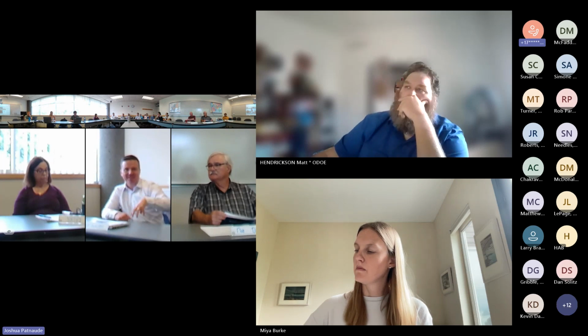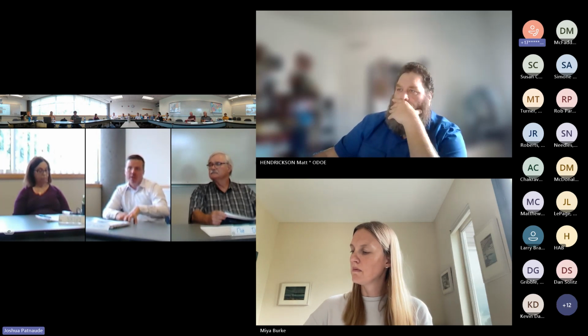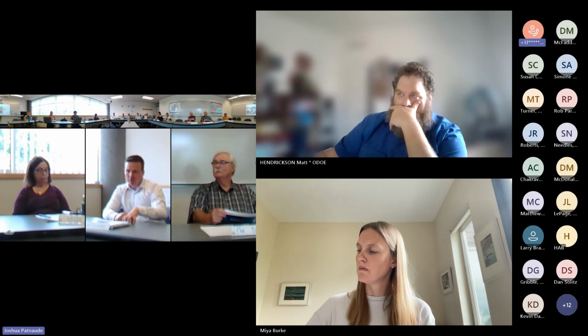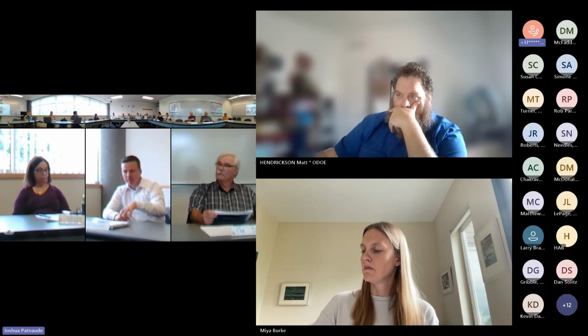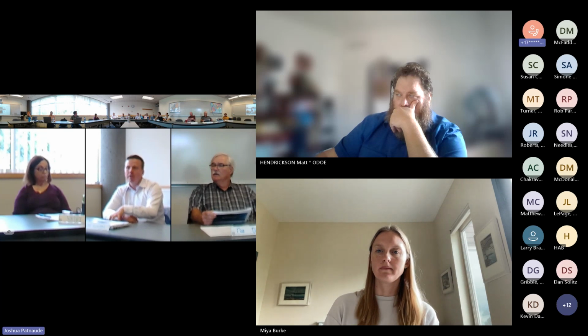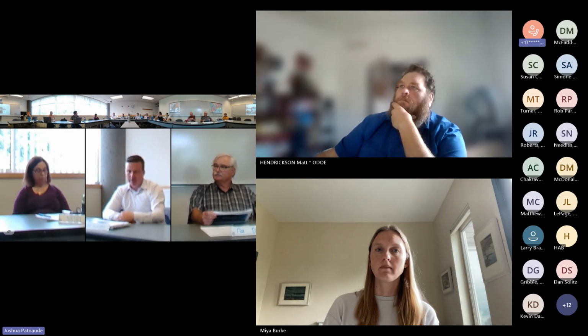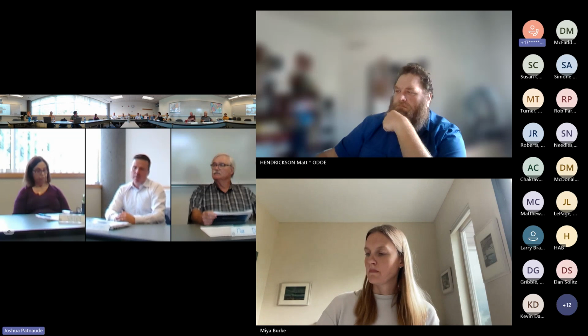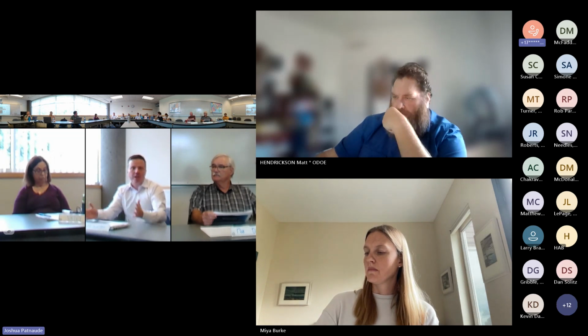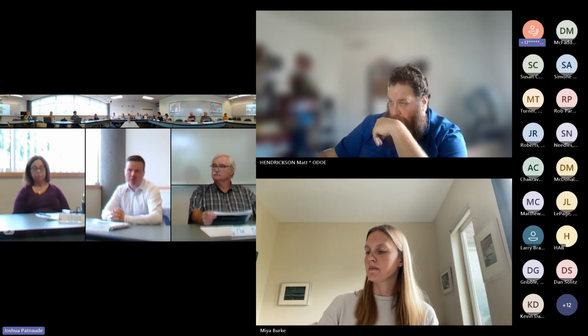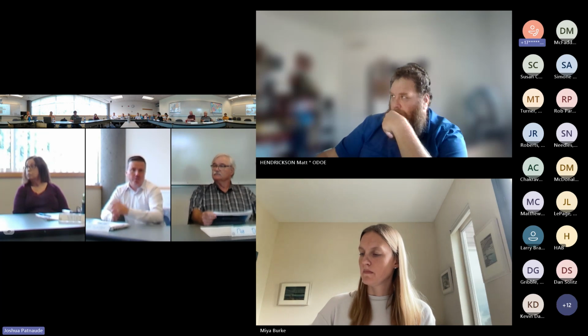So everyone's getting all the information of here's what we're seeing. We did some developmental work, some screening work with a simulated SY-101 waste composition, to see how your treatment method worked for it. They did what they were intended to do. And then it's into questions of, like Dan highlighted, if you see changes in waste composition specific to West Area, if we see any changes in the formulations. I don't anticipate changes, but that's work that we're doing for the contractor.